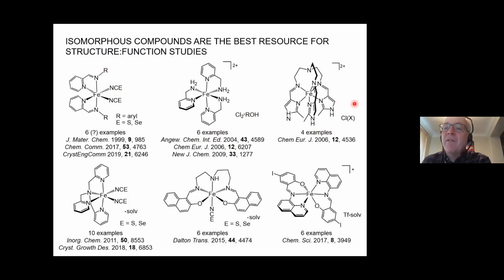Which is what they've done here, and always get series of materials with the same crystal structure. And if you're unlucky, your isomorphous crystals all have the same basic spin crossover. So these guys are all very gradual and really not very informative. Their properties are all pretty much the same, and it's difficult to learn very much from those cases. But in these ones, you get much larger changes from changing the solvent or changing the anion or changing the substituent. And here now you can compare your crystal lattice, look for small changes, and understand why those small changes lead to very different spin crossover.